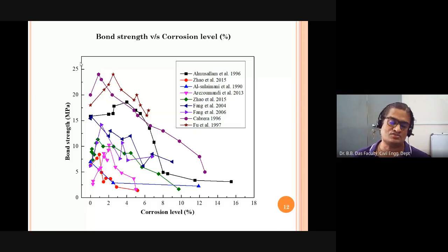But the moment the percentage corrosion level increases, there is a drastic reduction in the bond strength of the reinforced concrete. You can see many researchers' work plotted here, and this is exactly proving the mechanisms of corrosion that I just spoke about. Imagine the theory that we thought of, we checked with the researchers' data, and it is matching. In the initial stage of corrosion, because the concrete is not yet stressed, it is pre-expansion. Rather, the space between the steel and concrete is getting filled up with the material, so the bond strength development is happening slightly better.